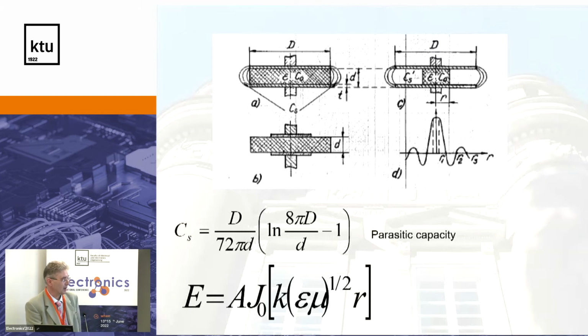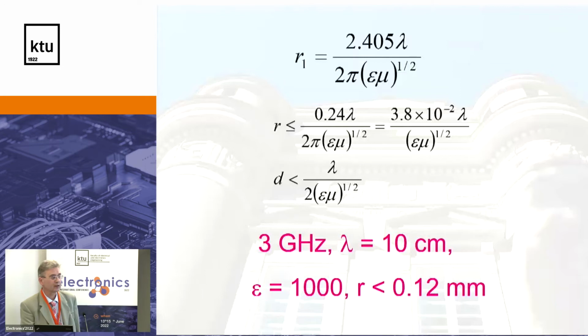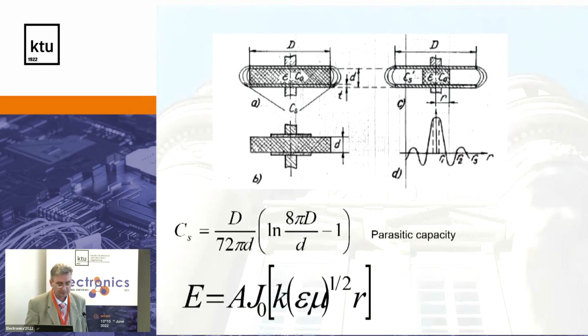So for such capacitance we go to such a formula where the electric field distribution, as I mentioned, is the zero-order Bessel function, where K is the propagation constant, epsilon the electric permittivity, mu the magnetic permeability, and R is the radius of the sample at the end of the coaxial line. So this is the first iteration, very simple. And then you calculate what the radius of a sample should be. Then we can go to the first maximum.